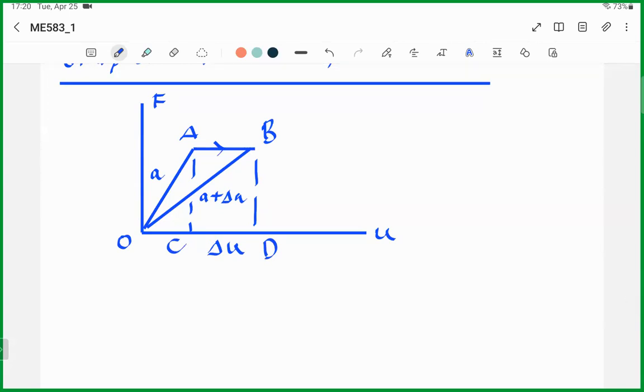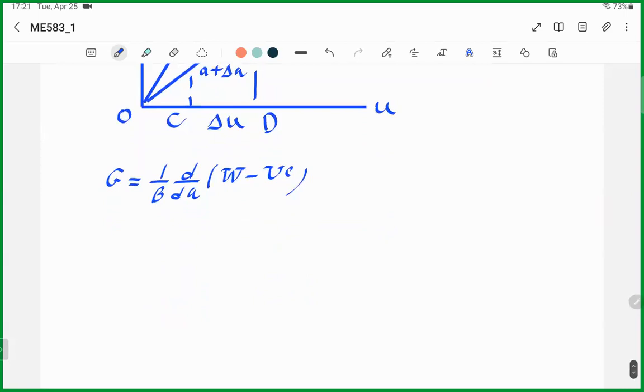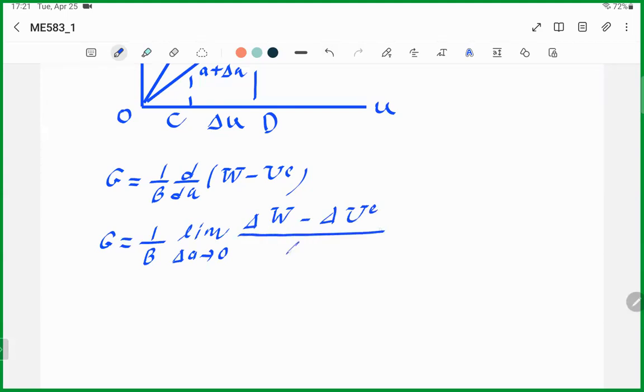If you recall the original results for energy release rate, G is 1 over B, d/dA of W minus UE, is that right? The difference between these energy terms is available for fracturing the specimen. In terms of the limit definition of derivative, or the method of increments, the basic method, I can write this derivative as limit delta A goes to 0, delta W minus delta UE over delta A.